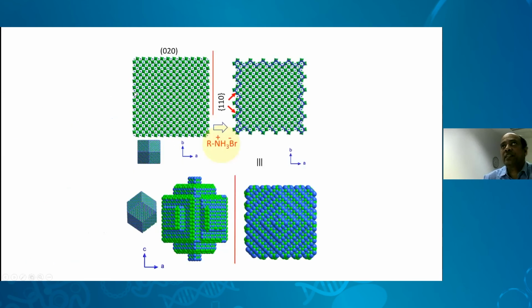We put the crystals here. All that is zigzag, coming out on both sides. And when we put the 3D models, we found this. These are two different views. You could see that AB, so that means this one is along the C direction view. And this is AC, the B direction view. They look like this. So beautiful crystals, just as a matter of using what kind of organics in the treatment in the reaction flask.